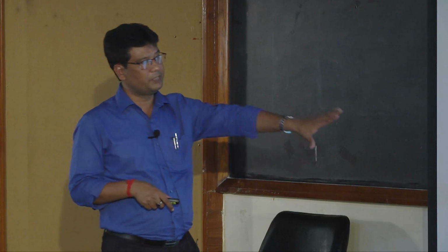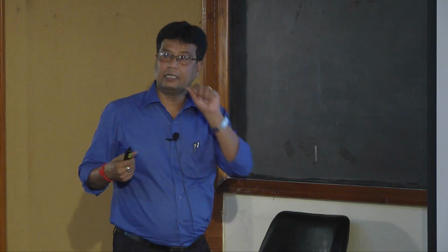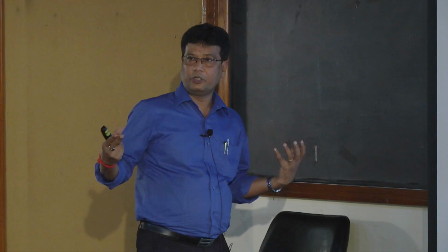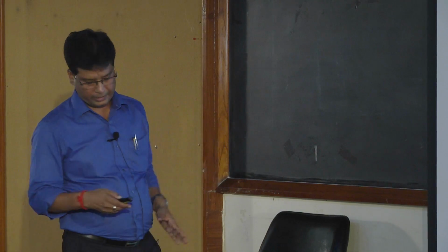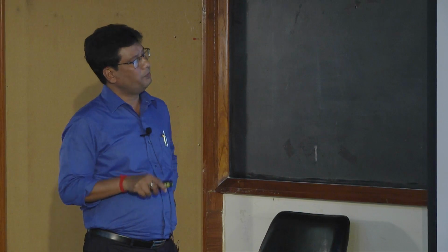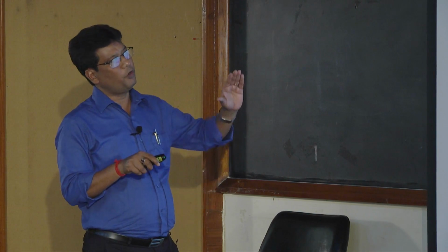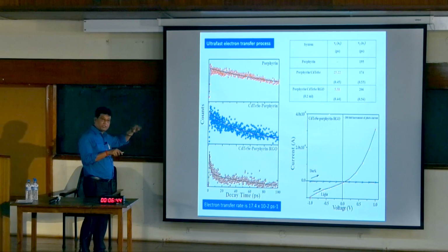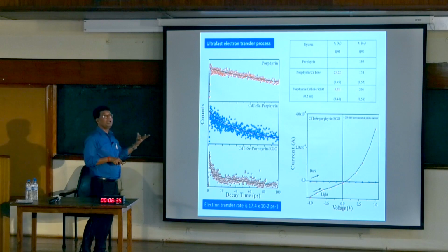Based on this, we have seen there is a photocurrent generation, because of the charge separation, because of electron transfer from the porphyrin to the graphene state. And from the ultrafast spectroscopic study, we have seen it takes 25 picoseconds from porphyrin in this system, but when you put the quantum dot, there is a very fast electron transfer process, because of the cascade electron transfer, 5.58 picoseconds. As a result, you can generate a photocurrent, a 200-fold increase of the photocurrent. That material could be used for a light harvesting system.